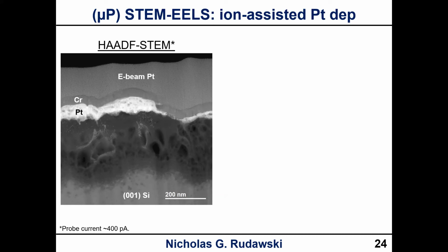So you can see that the platinum is kind of discontinuous. You can see that you have this structure in the silicon, which is kind of wispy and porous. Porous, there we go, that's the better word. And then it looks like it's almost exploded in a way. So what's going on here chemically? The chromium was a protective coating put on before making lamellas, then the E-beam platinum is from the lamella